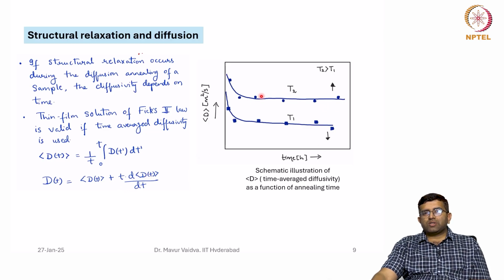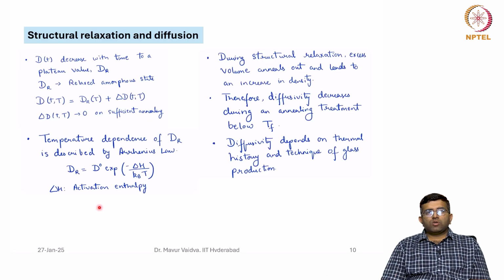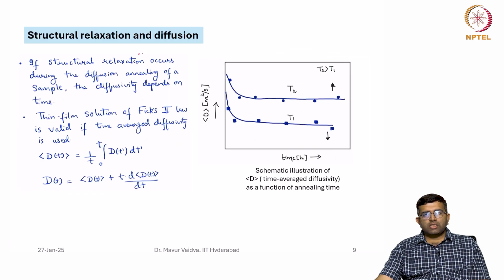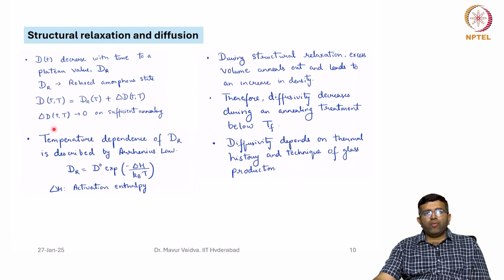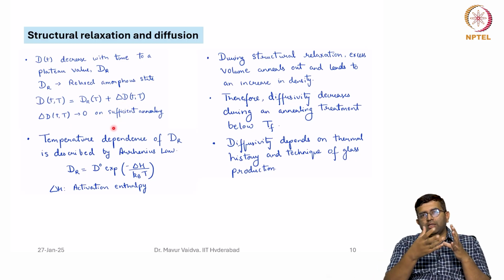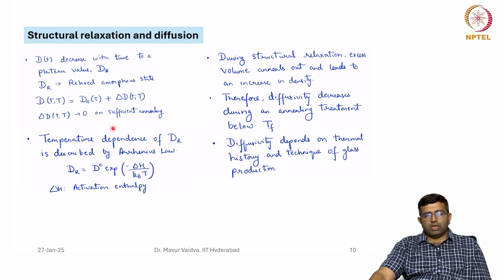So schematically it can be illustrated like this: at any given temperature the diffusivity will decrease and attain a nearly constant value. If you increase the temperature, the diffusivity will increase. Also, D(t) decreases with time to a plateau value D_R. So you see here that in this case the diffusivity is actually decreasing. It reaches this plateau value D_R, which is the diffusivity in the relaxed amorphous state. So you can write D(t) = D_R(T) + delta D. Delta D is 0 if you anneal sufficiently, which means that the instantaneous diffusivity has reached the relaxed amorphous state diffusivity. The temperature dependence of D_R is described by D_0 times exp(minus delta H by k_B T), where delta H is the activation enthalpy.